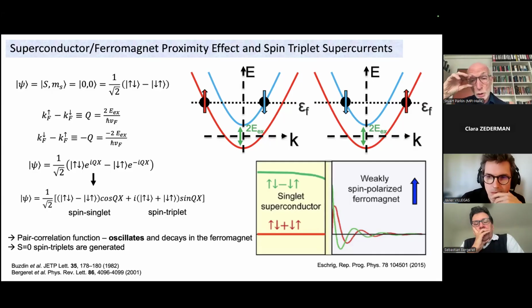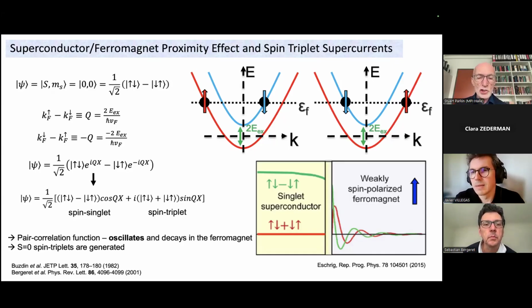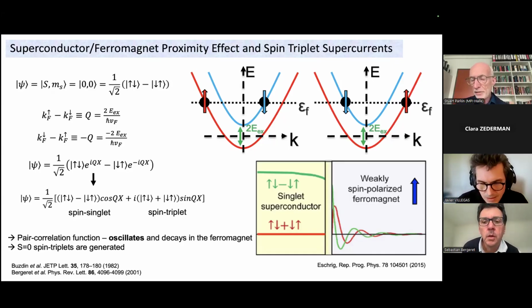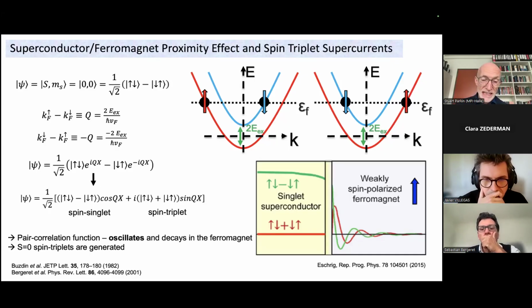So now, if we want to form Cooper pairs with electrons at the Fermi energy in this cartoon, you can see that they would have distinct momenta. So to form a Cooper pair with electrons with opposite spins, there would be a net momentum. And this net finite momentum gives rise to a very interesting finite momentum Cooper pairing state, which Sébastien demonstrated in the ferromagnet now consists of two components. You have a spin singlet conventional superconducting component, but you also now have a spin triplet component. Here, the spin triplet component will be in the S equals 0 state. Nevertheless, in the Cooper pair, the two spins are basically parallel to one another.